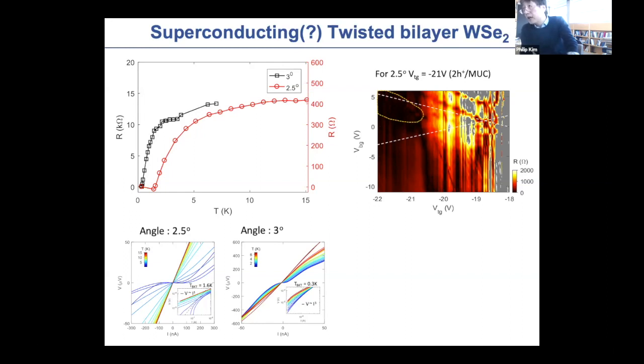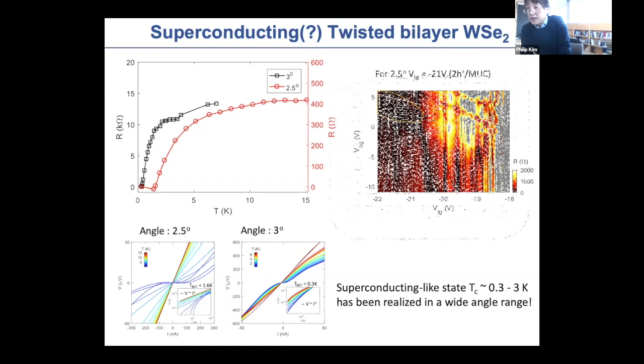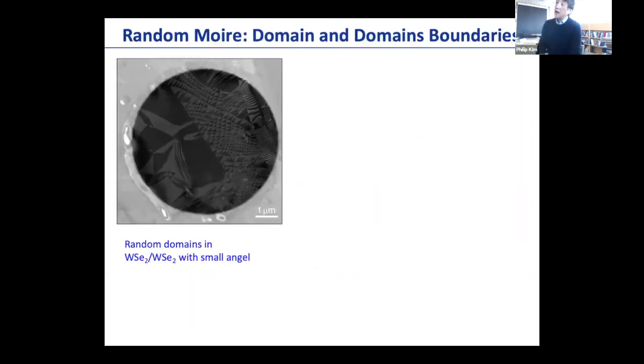So that's one of the issues. Part of the problem we are facing with such complicated behavior is that when we stack these samples together, it's very difficult to avoid a distribution of built-in strains, and built-in strain naturally ends up with this angle modulation. This is one of the extreme cases that I'm showing you, in the twisted bilayer sample that we target, something like 0.5 degrees or 0.4 degrees.